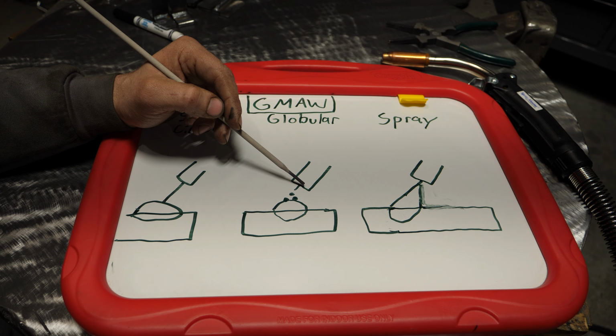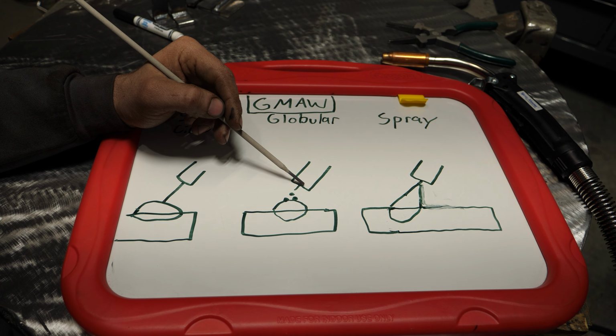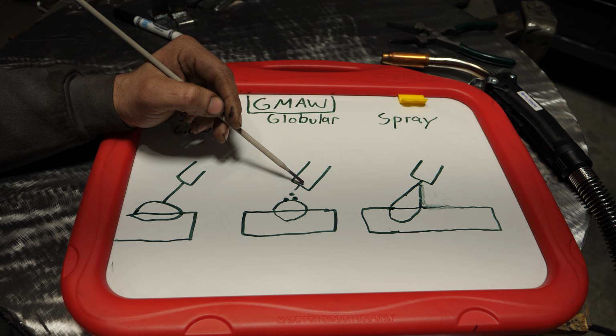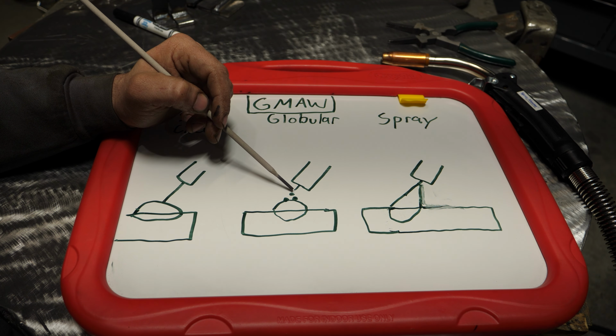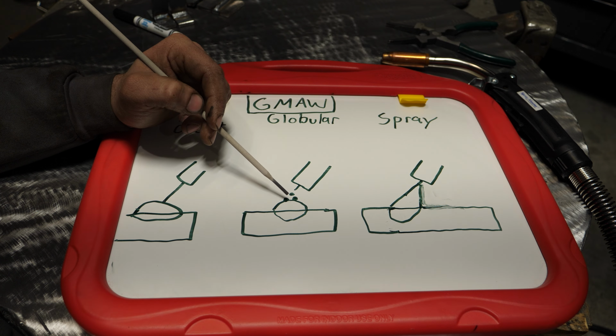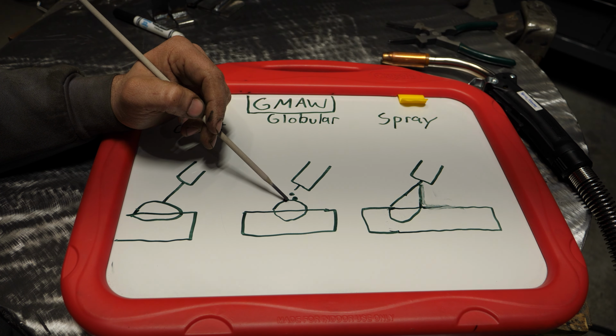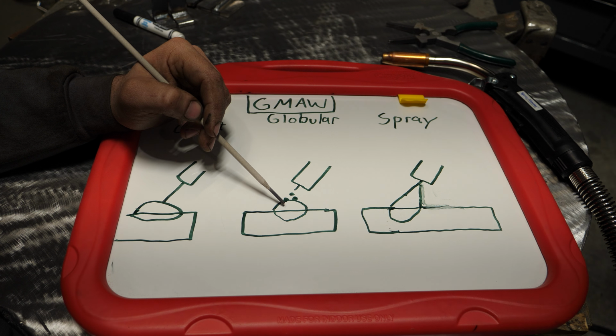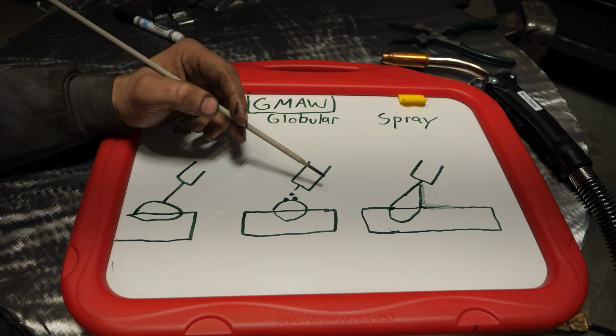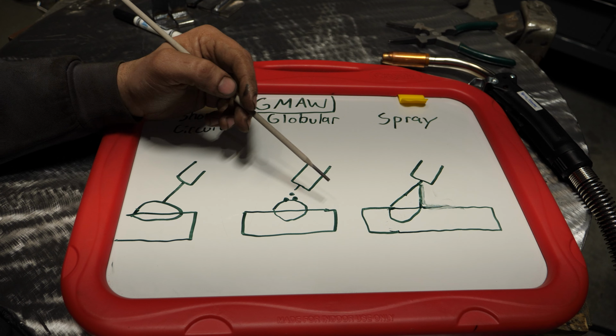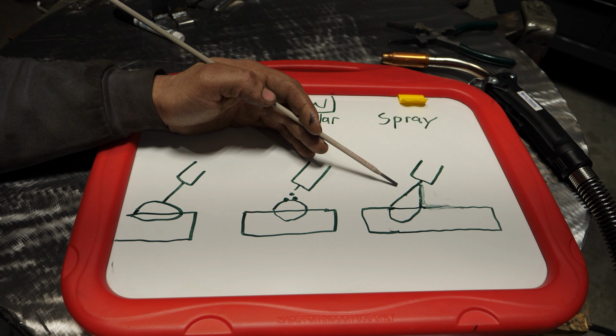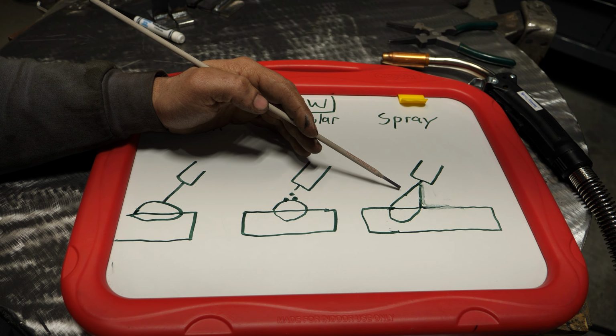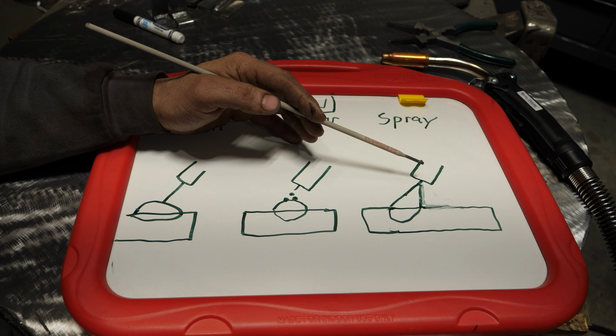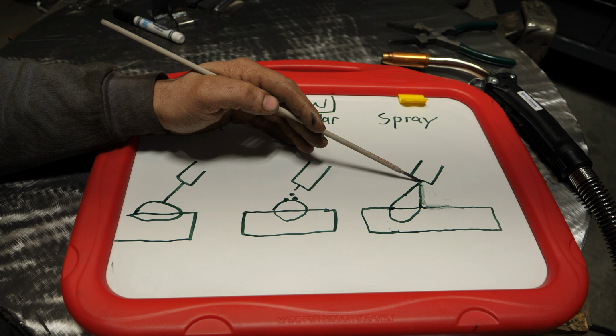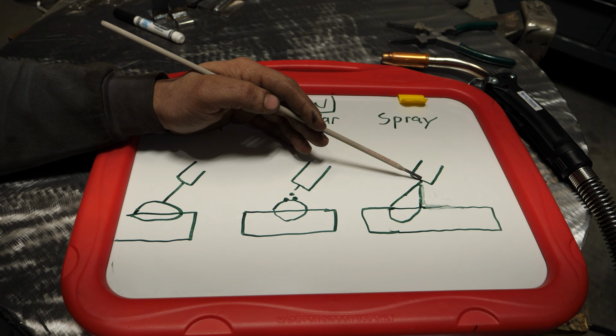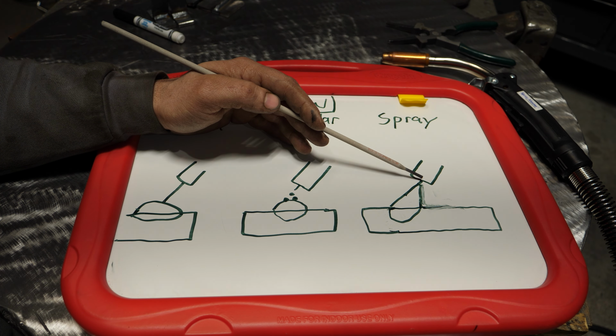Globular transfer is something that a 200 amp class machine might be able to achieve with like .030 or .035 wire. It's possible, but again, you need 100% CO2 and you'd be at the limit of what the machine would handle. But again, the end result of more spatter may not be desirable. And that's where spray arc, which is what we're going to talk about in this video, primarily comes in. Now, this is a poor drawing, but with spray arc, the wire is only solid inside the contact tip and the liner as it gets fed there.